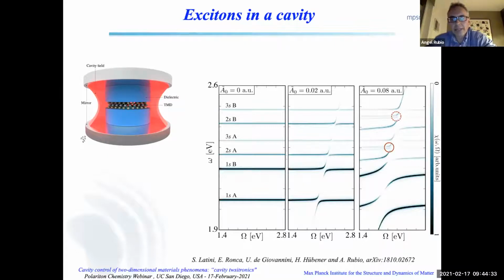It depends on which is the material. In some of those 2D materials, the dark states are very close to the bright ones on the bottom. And in those cases, they do play a role in controlling the dynamics. In the cases that you were describing, you're right, they tend to play little role, because they are at high Q. But the ones that we are looking at are states that get extremely close to the bright. And in some of these 2D materials, there are cases in which, if the thickness is big enough, the bottom of the exciton series is dark.